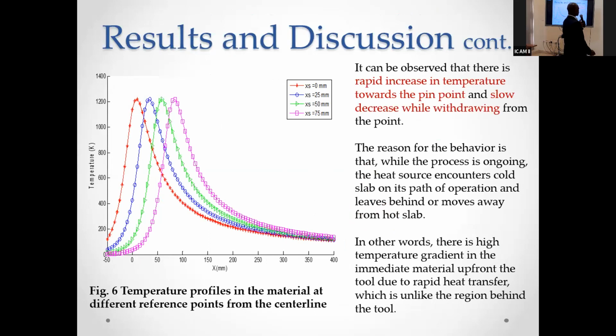So the next slide. At this point, what we did was to pick X and compare at 0 millimeters, 25 millimeters, and 50. We observed that there's a rapid increase in temperature towards the pin point and a slow decrease as it draws away from the point. In other words, as each point is moving, there's a high temperature gradient at the front of it. After it, because it has to cool down, the gradient is not as high as at the point.